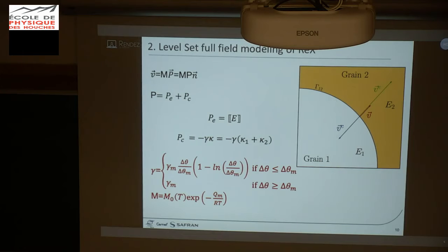And it is necessary to take into account this driving pressure, which is defined by the energy stored during deformation. And the second driving pressure, which is related to capillarity, is classically defined as the product of the grain boundary energy and the mean curvature of the grain boundary interface. One traditional mistake in the state of the art is the sense of curvature in 3D. Don't forget that in 2D the curvature is a scalar, but in 3D the curvature is a tensor. Okay? And what we call mean curvature in capillarity in 3D is the sum of the principal curvatures in 3D.